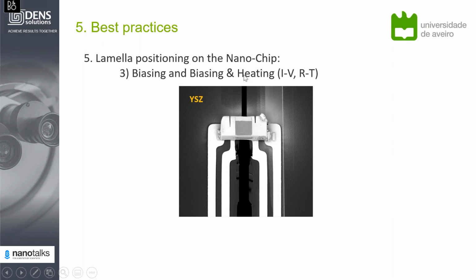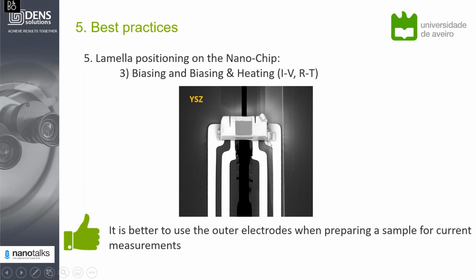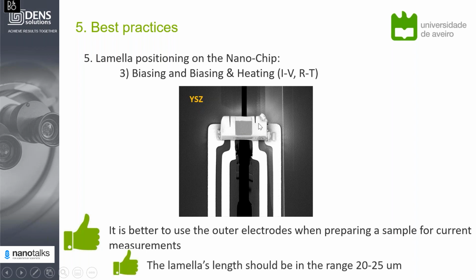For biasing and heating samples, when you're interested in IV measurement or RT measurement, what you can do is prepare the lamella on the outer electrodes. And in this case, you do need to make two contacts with the biasing electrodes of the chip. So this sample is actually yttria-stabilized zirconia. It's an oxygen ion conducting electrolyte, for specifically our biasing experiments at high temperatures. The length of those samples should be in the range of 20-25 microns.